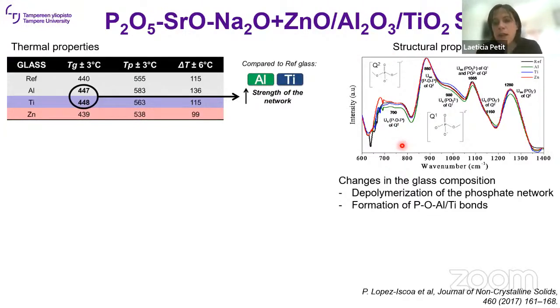In the case of aluminum and titanium, what is happening is we break the POP bonds and we create some new bonds, PO-Al or PO-Ti bonds. And it's because of the formation of these bonds that we have an increase of the glass transition temperature. Zinc in this case, because it has no impact on the glass transition temperature, is expected to act as a modifier and not as an intermediate.